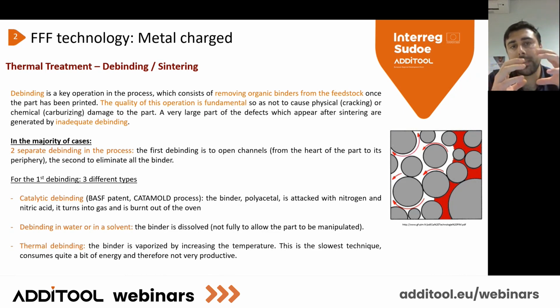And the debinding consists of removing the organic binders from the feedstock once the part has been printed. So the quality of this operation is very fundamental. Okay. And all the fissuration, the cracking, all the damage on the part at the end of the oven, when you open the oven, is due generally to a bad debinding. Okay, a very large defect which appears after sintering is generated by an inadequate debinding.